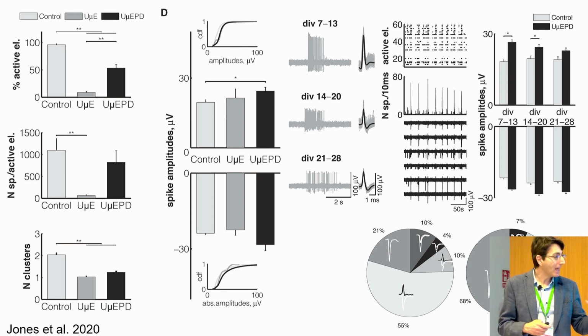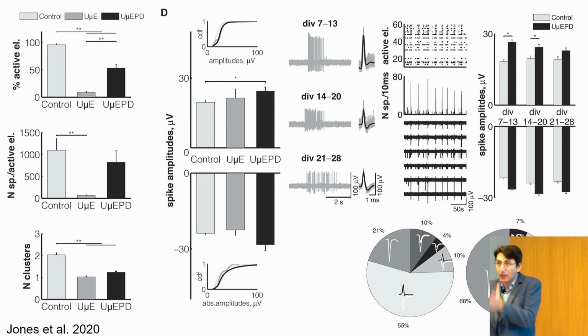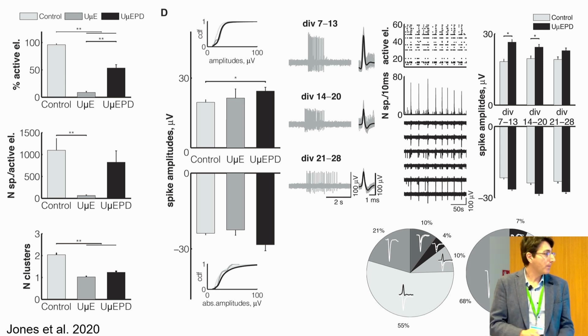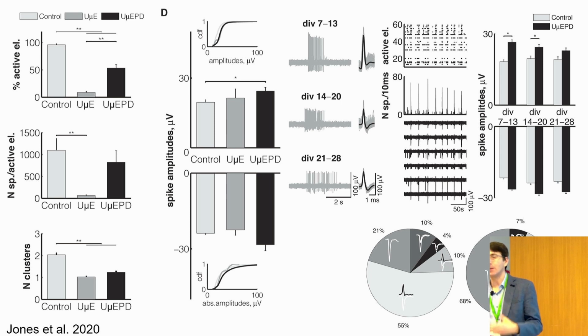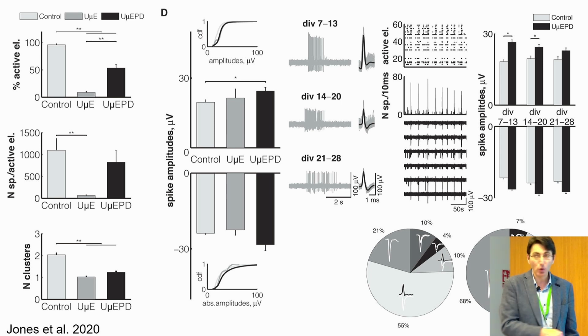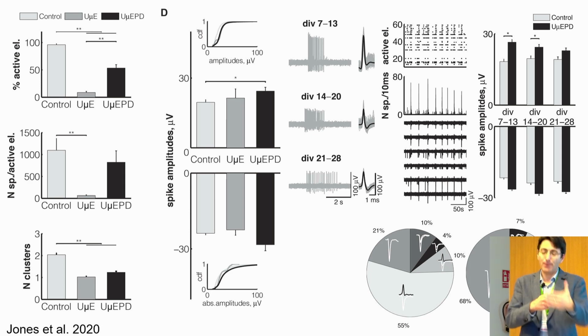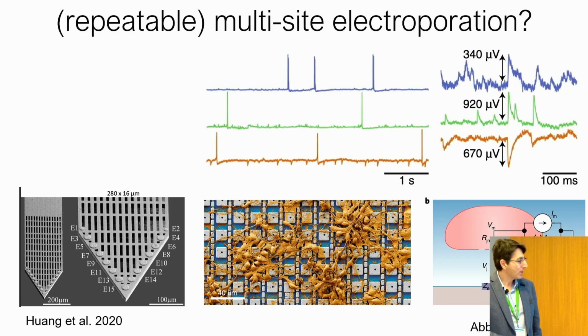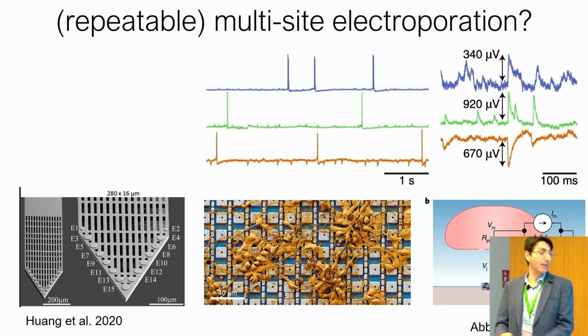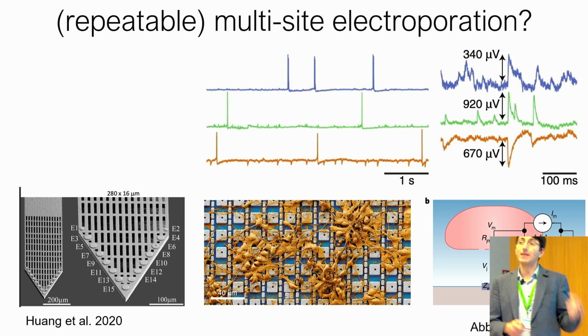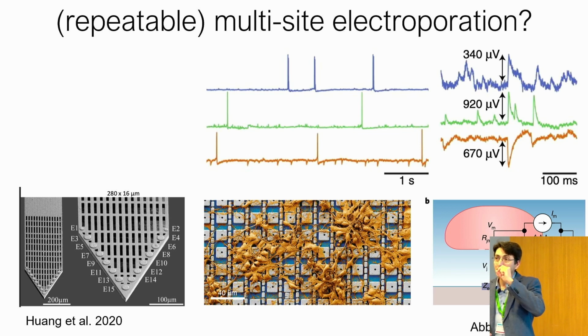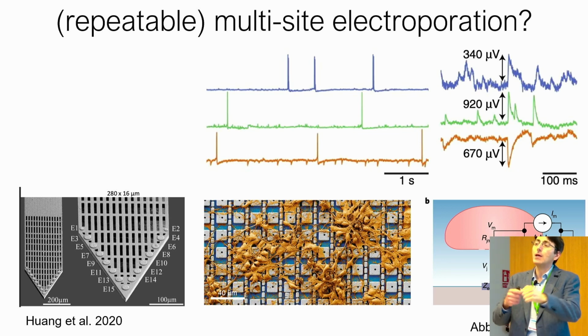So maybe the problem of spike sorting, which is crucial for neuroprosthetics, particularly for prosthetics for restoring movements and reading out signals, reading out thoughts and intention from patients, could be solved technologically by looking at these novel ways to interface electrodes with the material. Just for the sake of completeness, a few years ago, recording access to subthreshold activity was achieved, at least transiently, by this group of researchers that, however, did require electroporation. This was a fantastic work, yet requiring to pass and to damage the membrane, perhaps irreversibly, to open holes in the membrane.